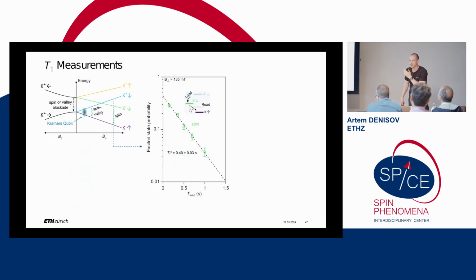So let's start with just a spin blockade at 135 millitesla. Very simple, just 2 states blocked by spin. So this excited state probability is plotted as a function of loading time. Indeed, it's exponential, and T1 is 400 milliseconds, which is already very long, an order of magnitude more than ever measured before in graphene. And that's due to the fact that we got a dot which is really decoupled from the leads, so it doesn't feel electrons in the reservoirs. But this wasn't our goal.